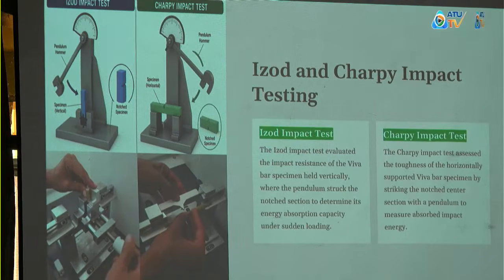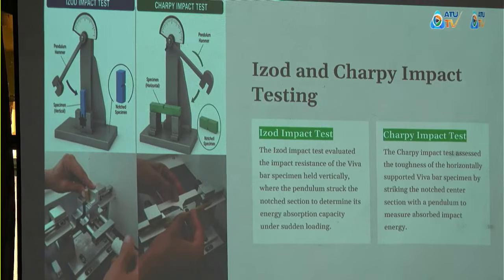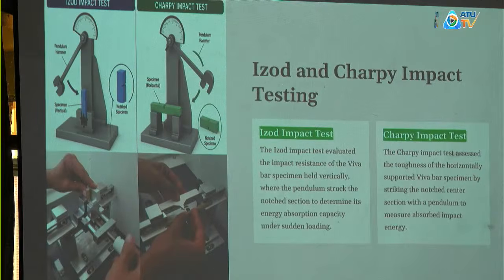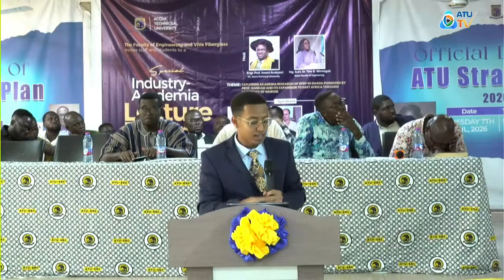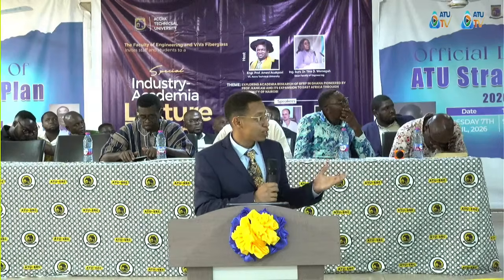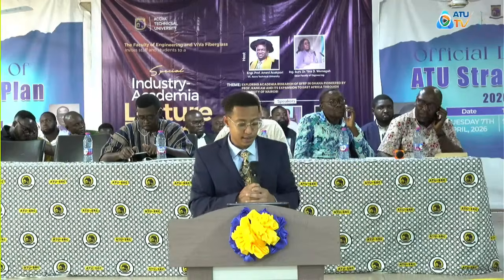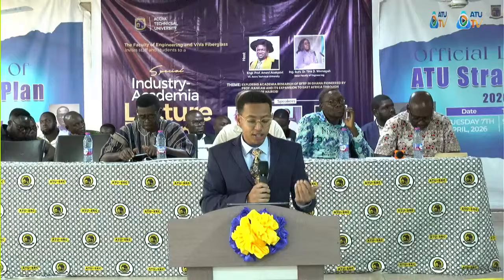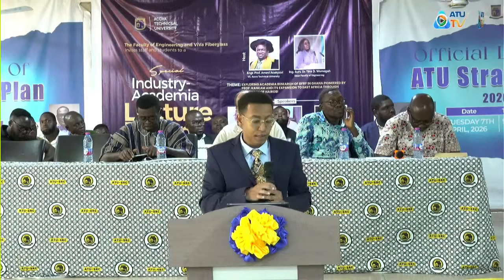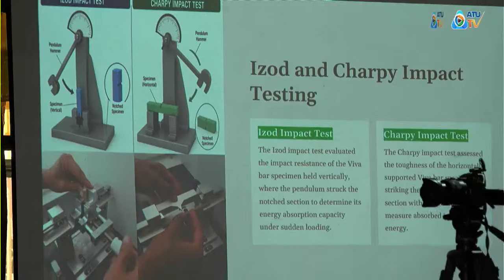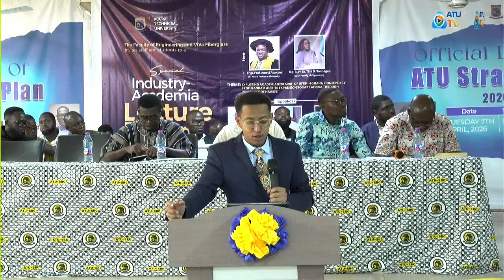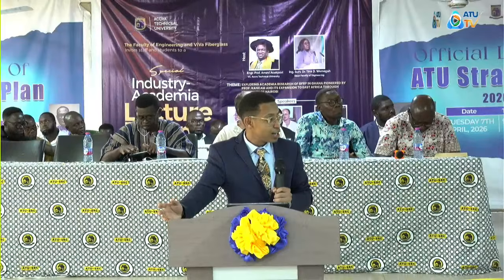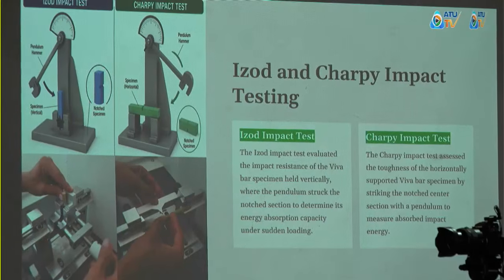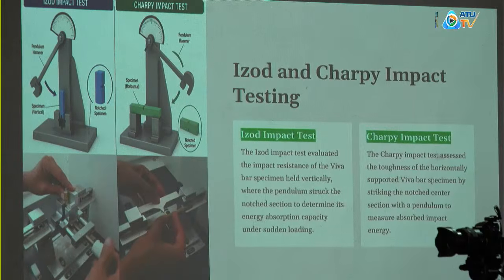To be specific, the Izod test evaluates the impact resistance using a vertically fixed position, and the Charpy uses a horizontally supported specimen to evaluate the toughness through the impact energy absorption. One important observation when I was doing this test is that the Viva bar did not fracture completely. It did not completely disintegrate, unlike the other specimens that are put in that machine. This behavior is important because it indicates the internal energy absorption. It also indicates the crack resistance and progressive failure characteristics.